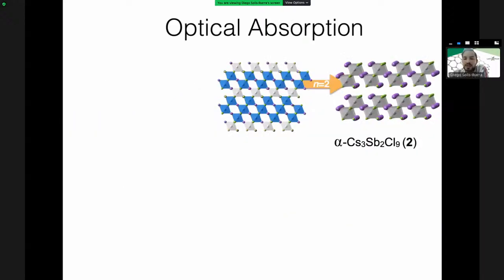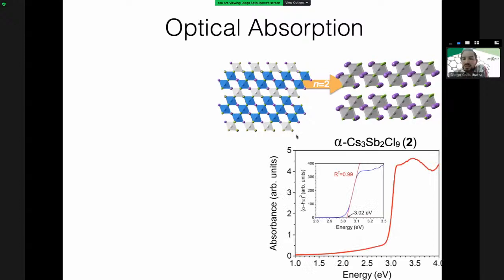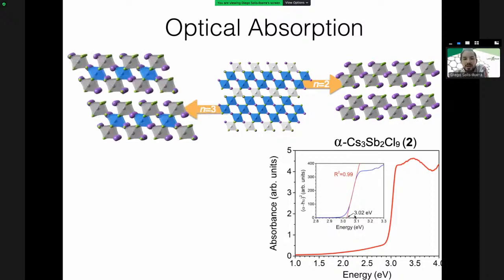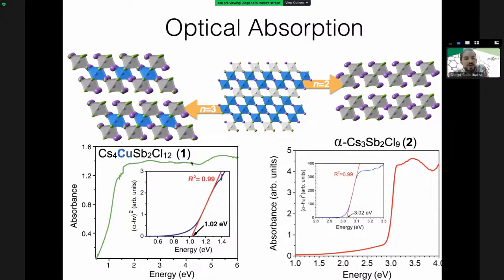And what was really surprising is that the prime material, the one which has only antimony, has a really large bandgap of about 3 electron volts. But what we found is that our material, once we incorporated copper, it has a much smaller bandgap of about 1 electron volt. So this is a really drastic difference between these two materials. And of course, when you're talking about 1 electron volt, you're around the region where making solar cells become something interesting and something definitely possible.